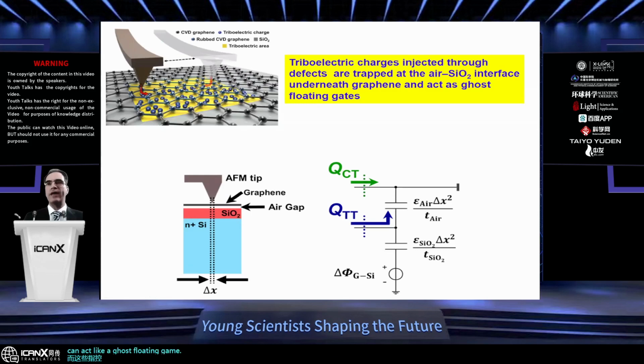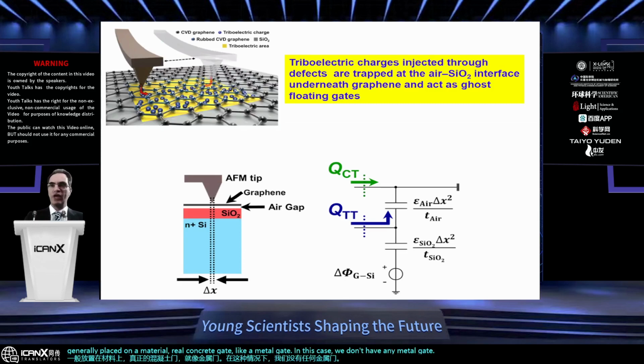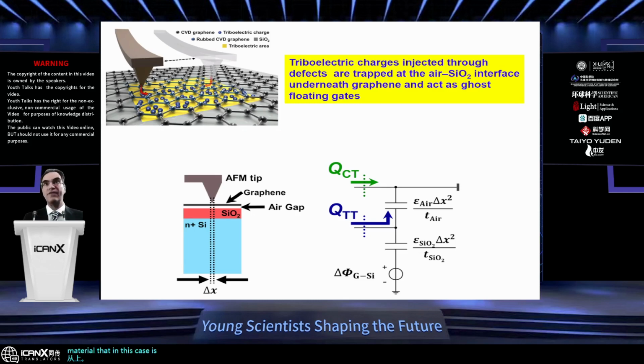So it's similar to the charge that is generally placed on a real, concrete gate, like a metal gate. In this case, we don't have any metal gate, but we have some charges that are trapped on an insulator at some very small distance from the material, that in this case is graphene, and can still act as a ghost floating gate. We call it ghost because there is no material, it's just the charges on an insulator. And these charges on an insulator, we can create, delete, and recreate at will, so that we have some ghost floating gates that can be defined on demand.